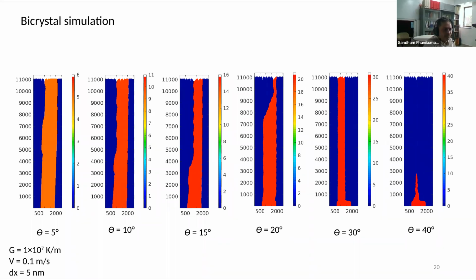Now we also can do bicrystal simulations to show how the space between two grains helps the liquid be present to fill the space and lead to prevention of crack or not, etc. So all those things can be done. So here is an example to show you that when there are grains that have very small misorientation, it allows for the liquid to be present all through. Whereas if you have a high misorientation between grains, then the liquid is present only in a small region between them. So it is not having access to the rest of the liquid away, which means that when this region solidifies, it can leave some void, which can lead to basically a crack. Okay, so that kind of an indirect estimate on the effect of grain misorientations on crack formation during the solidification can also be thought of.